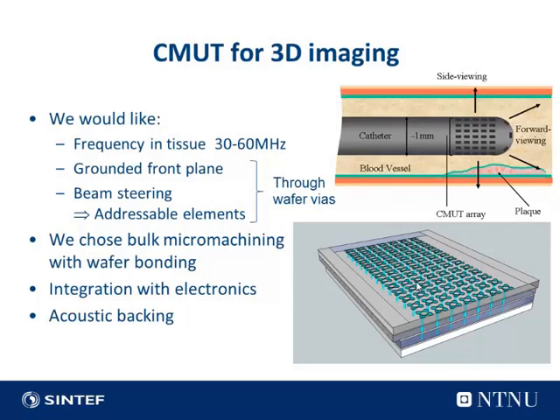So we have a frequency requirement from the application. For this imaging within the blood vessel, you will need a frequency of 30 to 60 megahertz to, we believe, be able to detect the plaque that we are looking for. Imagine putting this into your blood vessel. You would like to have the front plane grounded, which means that you cannot have the electrodes on the front side. You will need some vias so that you can control the elements from the back side.